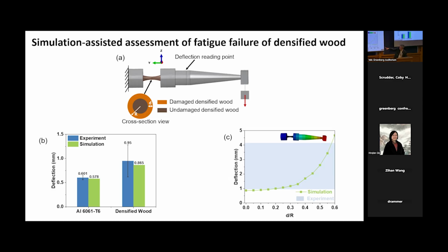So for the aluminum and for the densified wood, it agrees. The green one is the simulation prediction, the dark blue one is the experiment result. It agrees quite well. And the large variation of the densified wood tells you that wood is a natural material. The scattering definitely is higher than the aluminum engineering material, and more anisotropic.